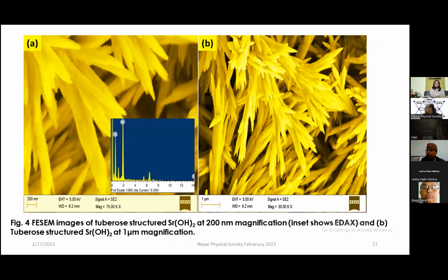High porosity, as it consists of secondary, ternary, and even higher order branches. One can see the secondary, ternary, and higher order branches here. That's why porosity is going to increase. If it is more porous, it allows the electrolyte to move inside and react. So it will lead to a higher specific capacity.